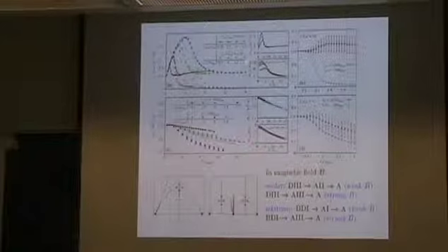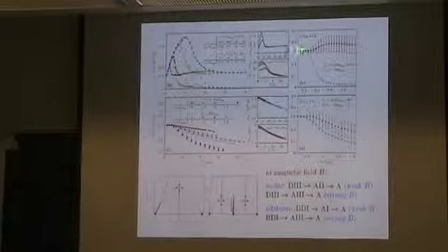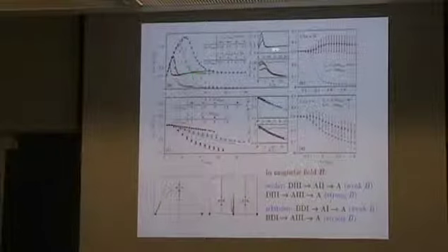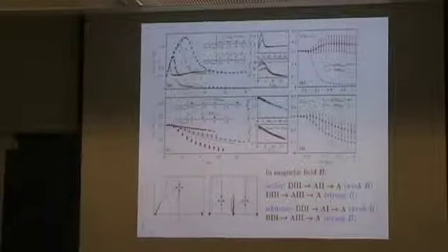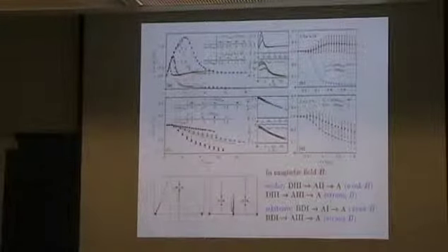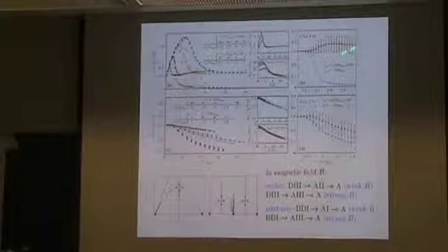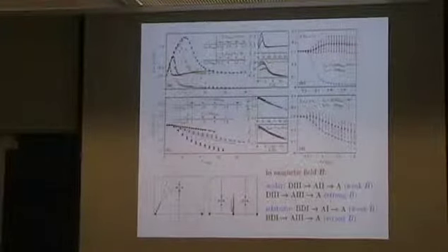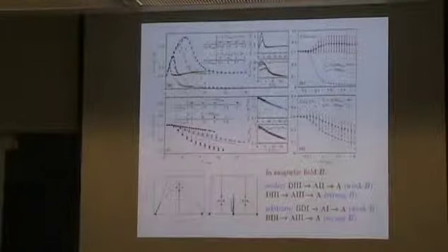So when it's symmetric, what we see is that we flow into some finite value of the conductivity, and it's also shown here, this finite value. So these are not error bars, that's maybe a bit unfortunate. These are mesoscopic fluctuations that are shown here. So error bars for average conductivity are in fact very small. So it's just these red points, and this saturated value, which is now slightly larger than this 1 over pi, and that was the value on the previous plot, and that's exactly the value. So what we see here is that the system flows into the one-hole fixed point, as it should be.